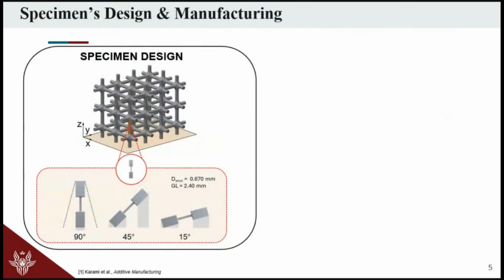To do this, we decided to adopt a bottom-up approach rather than printing overall lattice components. We decided to use subunital elements, so the smallest repeating units that we have inside the lattice, which are not the units themselves, but the struts. Why this? The reason is twofold. First of all, there is, of course, a saving of money in order to print less specimens in higher number. And second of all, because fatigue is a localized damage phenomenon. And so if we understand how the failure occurs and how the fatigue properties are inside these specimens, then we can scale up to the overall lattice component.